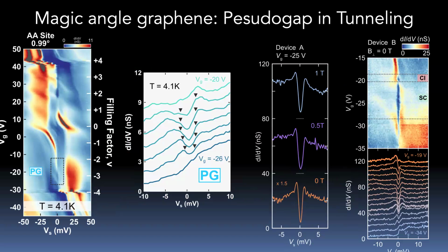But more interestingly, in this system, this is not like cuprates, because you can really kill the zero resistance state completely with just a Tesla. And you can stay at the lowest temperature and measure the spectroscopy, and you can see that this gap very much doesn't care about the presence of global superconductivity as far as zero resistance goes. So take this however you like. This is a pre-formed pair? I don't know. Is it another kind of order? Maybe. And you'll see that in the later part. Or this is something to be designed.